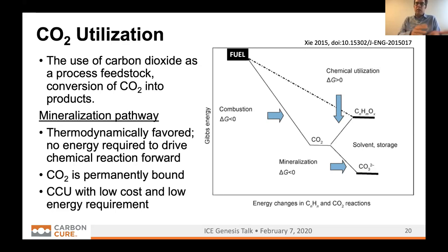To simplify this diagram on the right, we have a fuel. The fuel gives off energy, but it also gives off CO2 when you are combusting it. Now you have the CO2, and you can do two things to it. You can either turn it into a chemical, which is going to require additional energy to break the carbon-oxygen bond, or you can turn it into a mineral. If you turn it into carbonate, this is a thermodynamically favored reaction. That means it will release energy, it will happen spontaneously, and it will also be permanent. Once the CO2 is locked in as carbonate, it's effectively permanent, and that's where most of the carbon in the world right now is: locked in as carbonate minerals.